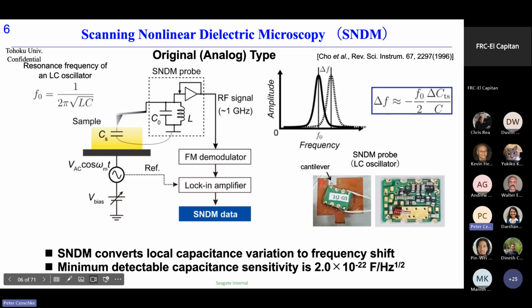And this is one example photograph of the SNDM probe. This is the back side of the probe. You can see this is a metal coated cantilever here. And this is the inside of the SNDM probe. You can see the inductance, and this metal area is a built-in capacitance, C0 and L here and here. And you can see two black parts, transistors. One transistor acts as the oscillator, the other transistor acts as the amplifier of the oscillating signal. Anyway, SNDM converts the local capacitance variation to frequency, and the most important thing is the signal to noise ratio. The minimal capacitance sensitivity is about 2.0 times 10 to the minus 22 farad per root hertz order.